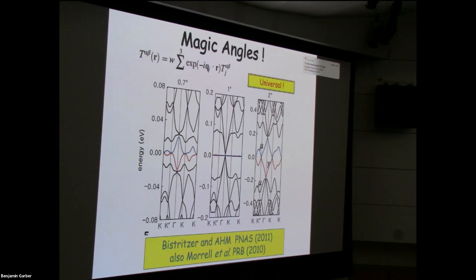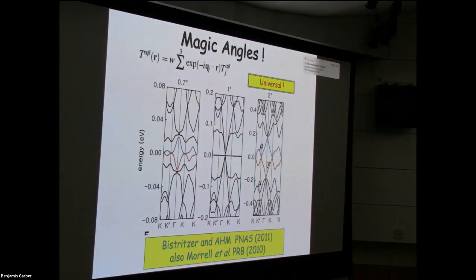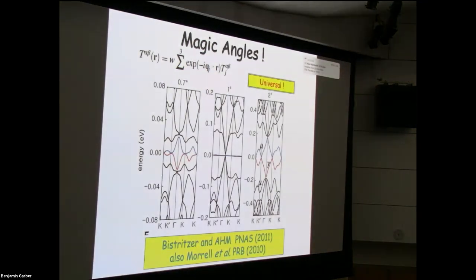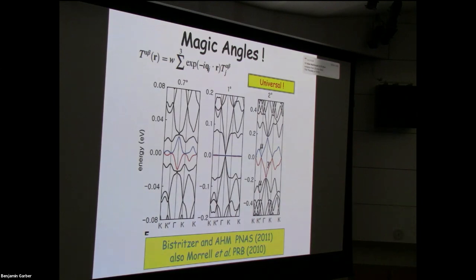And when the twist angle is large and the Moiré period is small, that tunneling Hamiltonian is varying rapidly in space, and therefore it couples together electron states in the two layers that have very different momentum. And one thing we know about graphene layers is that they have very large dispersion. The energy of an electronic state changes very rapidly with momentum. And therefore, at large twist angles, the two layers are almost invisible to each other. And they become more and more strongly coupled to each other as the twist angle gets smaller, and the Moiré pattern changes more slowly in space.